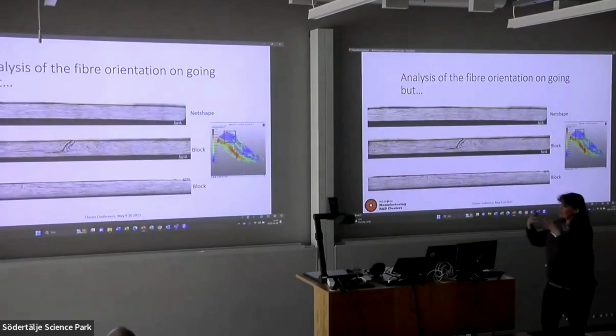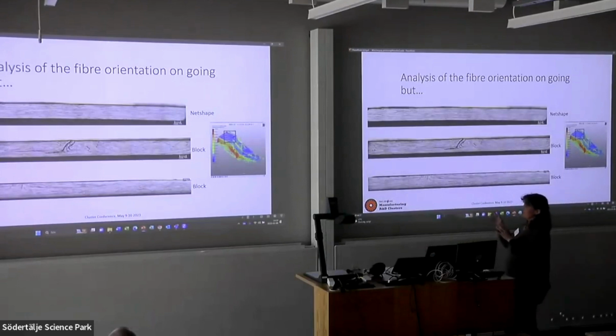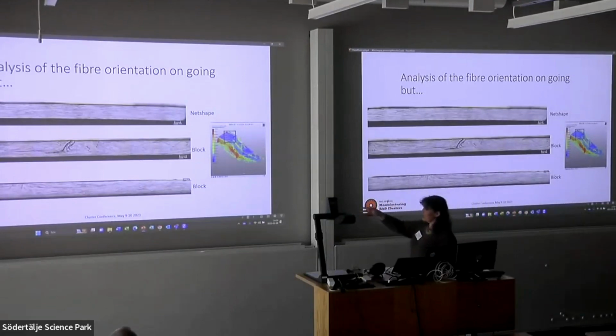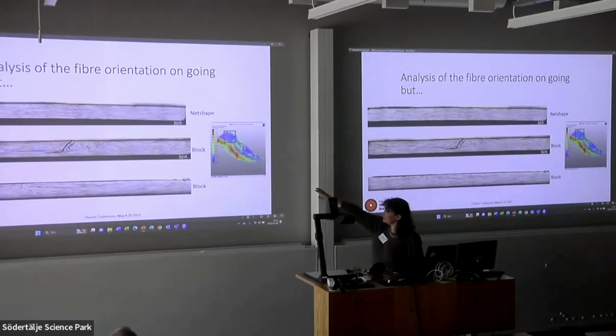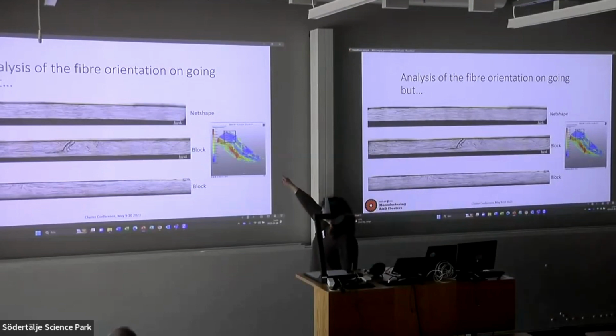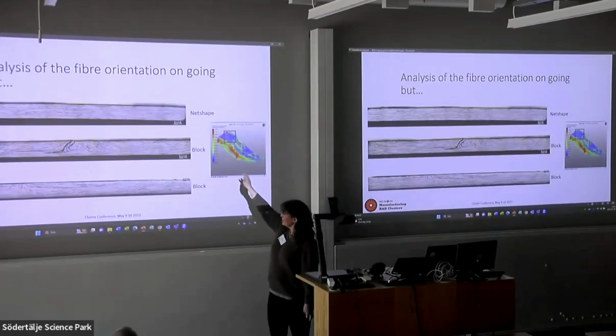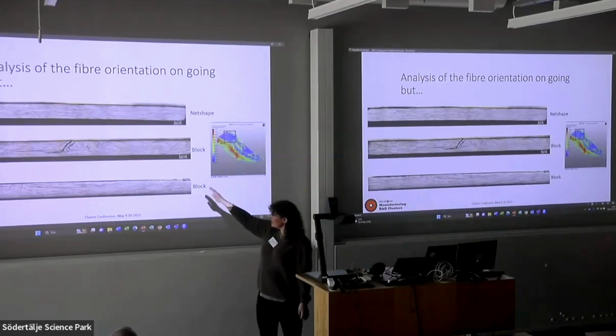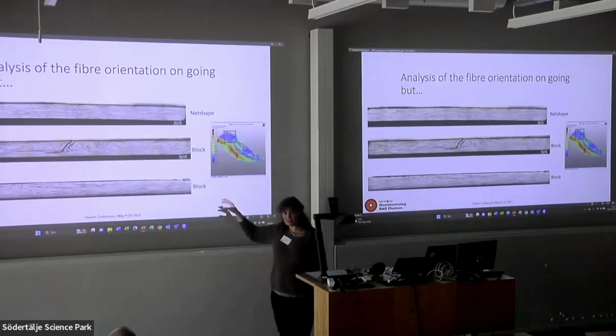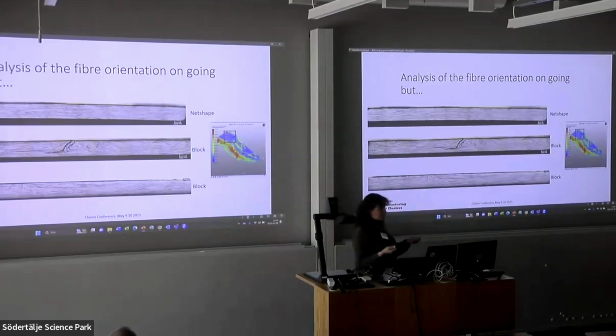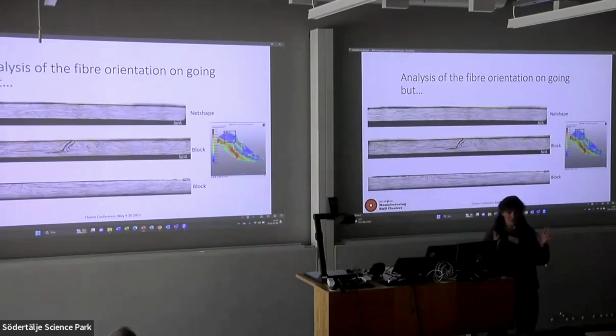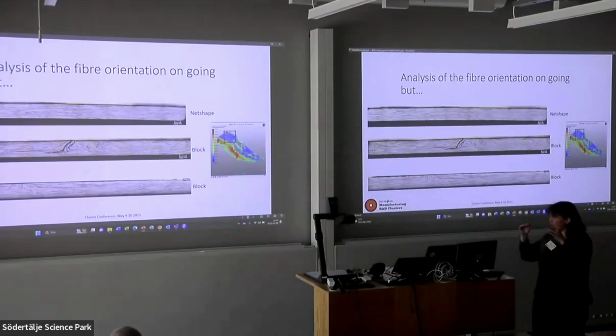We're also looking at what's happening with the fiber orientation and looking at the analysis. But the other thing we can see is the net shape, I've tried to show which area it was taken from, showed just a normal composite strip, but with the block, you can see there are some cracks in this part as it's being pulled down. This is nothing that you can see on the surface. It looks fine on the surface, but there are cracks in different places where the material has strained.